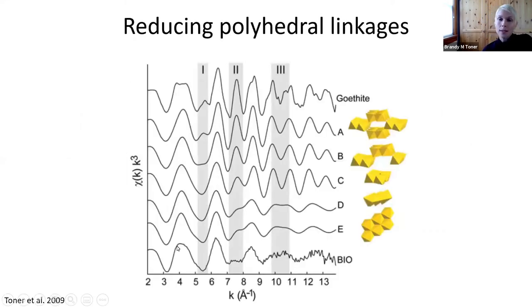I took two approaches. I of course made a simple shell by shell model to fit the biogenic iron oxyhydroxide, but I also took the goethite pattern, modeled it, and then said, all right, if we think about these iron oxyhydroxides from the polyhedral approach, what happens if we take a simulated goethite spectrum and start removing or reducing the polyhedral linkages that we know are important for creating the spectral pattern that it generates? And so you can model sort of from the bottom or you can take it apart from the top.